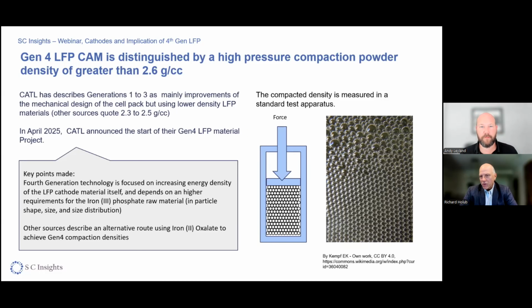Why is size important? The little graphic on the right just indicates that, for a packed bed of very uniform spheres, you're usually at around 38 to 40% void volume. Void volume is air space that's not useful for storing energy. To get that lower, you've got to go to a mixture of particle sizes to fill in those little gaps and also provide you the higher density we're going for. So that's just a representative graphic to give you a visualization of what we're talking about here. Next slide, Andy.